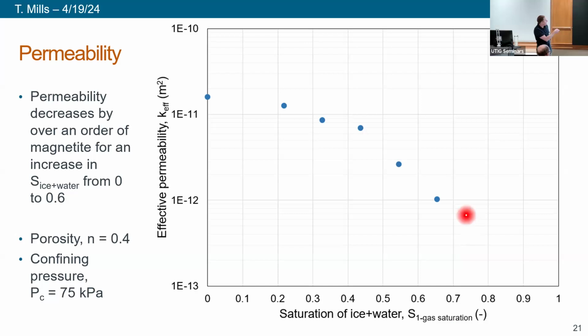And we can see going from our intrinsic permeability, or our permeability at a saturation of 0, as we increase the ice saturation, the permeability of our sediments is decreasing. And so we have over an order of magnitude decrease in permeability with an increase of saturation up to about 0.65. And so this was really nice to finally see after months and months of effort.